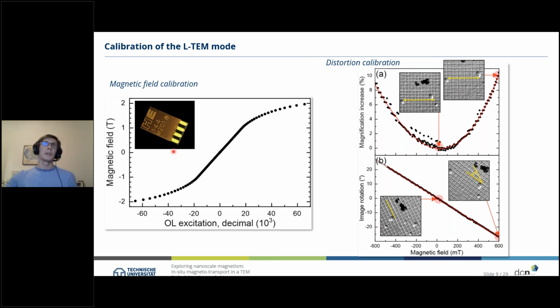So we calibrated it, then we mounted it into our TEM using the fusion holder and measured the magnetic field as a function of the objective lens excitation. That is what is plotted here on the bottom. You see that we have a very nice, more or less linear behavior for small excitations, and then it starts to saturate for higher excitation, when we reach magnetic field values up to 2 Tesla, where probably the pole piece starts to saturate, and that's why we also go into saturation of the generation of the magnetic fields.